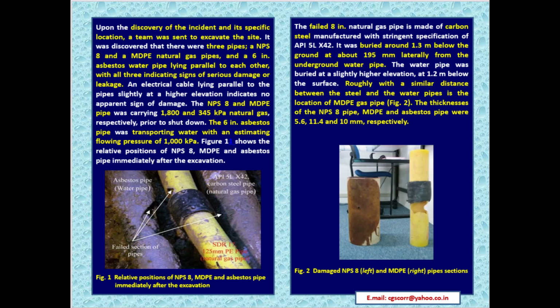The failed 8-inch natural gas pipe is made of carbon steel, manufactured with stringent specification of API 5L X42. It was buried around 1.3 meter below the ground at about 195 millimeter laterally from the underground water pipe. The water pipe was buried at a slightly higher elevation at 1.2 meter below the surface, roughly with a similar distance between the steel and water pipes is the location of MDPE gas pipe, figure 2.